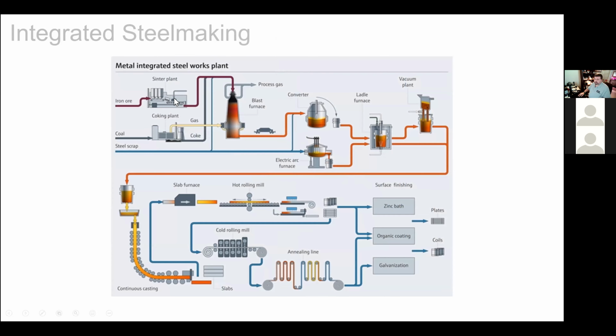So in an integrated steel plant, the core of the process are the blast furnace and the converter, the BOF. But you also have these other large facilities, the coking plant, which takes coking coals and basically heats them and drives off all of the volatiles to produce coke, which is charged to the blast furnace. And then you saw that in some cases, people, in addition to pellets and lump ore, are charging what we call sinter. So sinter is basically material that's produced in a furnace. It's kind of like a tunnel furnace. And material gets heated up and it actually sinters together.